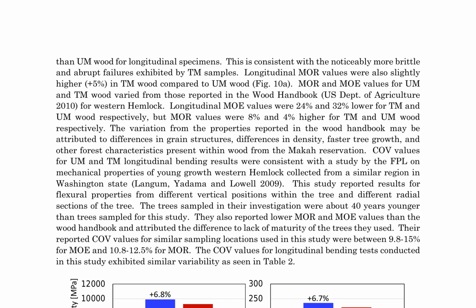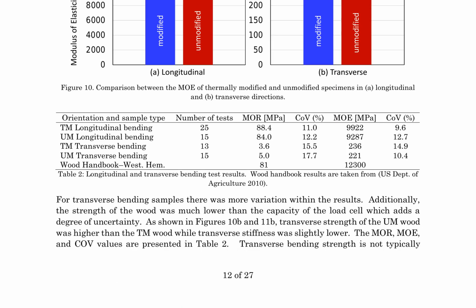Coefficient of variation, COV, values for unmodified and TM longitudinal bending results were consistent with a study by the Forest Products Laboratory, FPL, on mechanical properties of young-growth western hemlock collected from a similar region in Washington state. This study reported lower MOR and MOE values, attributed to the lack of maturity of the trees used, and COV values between 9.8 and 15% for MOE and 10.8 and 12.5% for MOR, similar to the results obtained in this study.